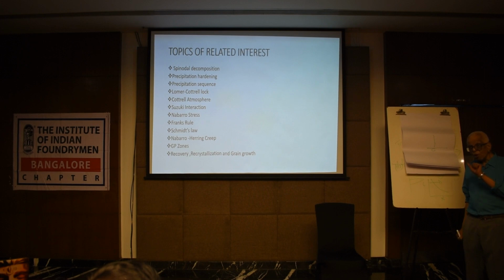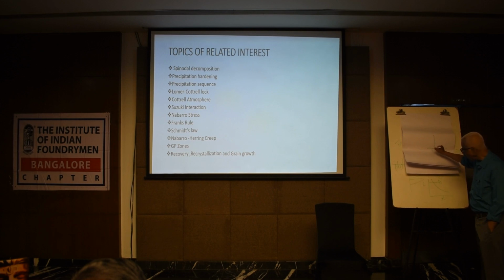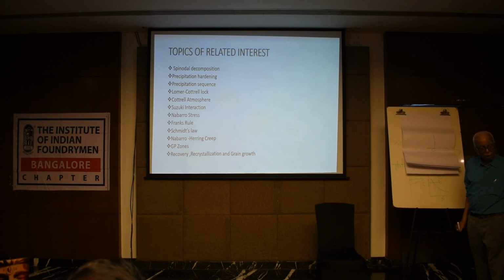The carbon atoms sit in the core of the dislocation. That's why you have the yield point phenomenon in steels. It's called the Cottrell atmosphere. Cottrell was among the first people to talk about that, long back. That's why you should read very old papers, because they talk about the fundamentals more, the 60s, 70s and 80s. So the Cottrell and Bilby model is that carbon atoms lock the dislocation.